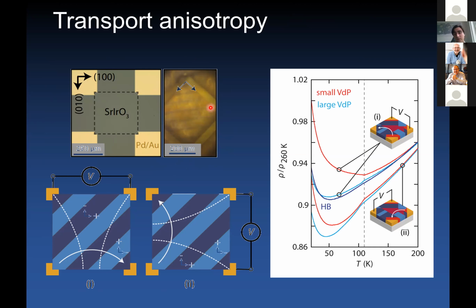By using polarizers in your microscope, you're able to resolve these domains oriented at 45 degrees with respect to the 100 and the 010 crystal axes of strontium iridate. If you do so, you see something very interesting: when you go below this transition, so when these domains form, your system behaves as a semi-metal along one direction and as an insulator along a different direction. So what is the cause of this anisotropy?